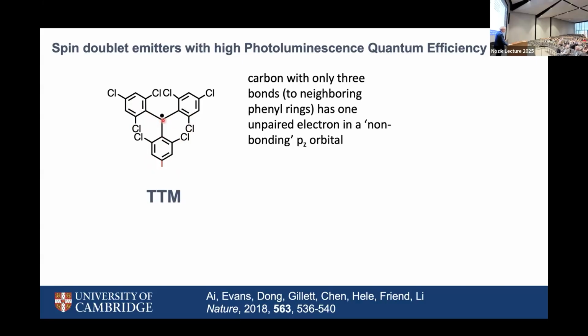And because there are only 3 bonds, there is a leftover electron, which isn't able to sort of pair up with another electron to make a double bond, because they're already paired up within the benzene rings. For this structure, where we have an odd number of carbons, the only option is that we have a spin that is actually quite confined to this central carbon. So it's a sort of pz orbital, and it has quite interesting symmetry protection. It is a non-bonding orbital, but in a very, very profound way.